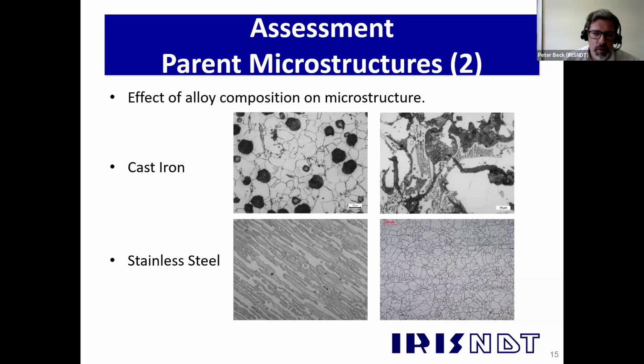So taking two extreme examples here, one would be cast iron. So these top two images show on the left spheroidal graphite cast iron, and on the right a grey flake cast iron. So as I say, both of these would be termed cast iron. The real key difference is the alloying composition. And the key effects of that are that on the left you've got these nice nodules of graphite, and on the right they form these flake-like graphite structures. There's various ways to document these. ASTM have a range of classifications. So they would classify the graphite into whether it's flake or spheroidal. They would classify the different sizes of graphite as well, and the grain size.